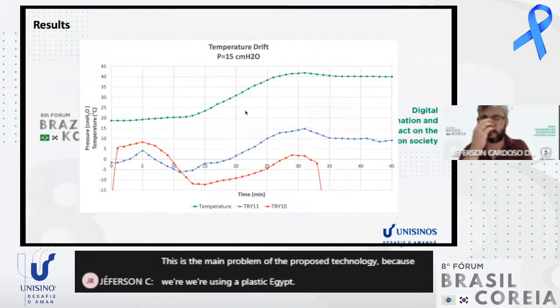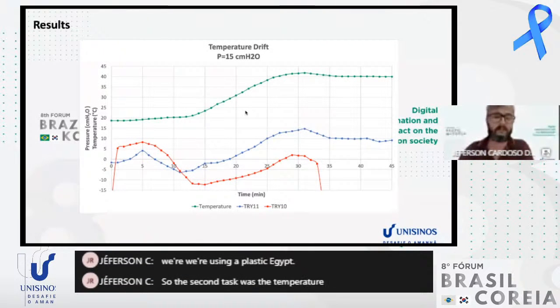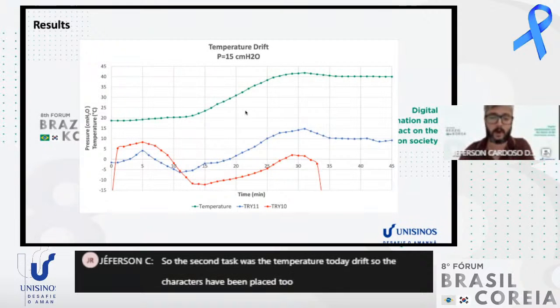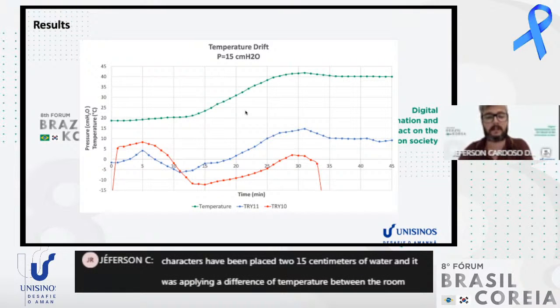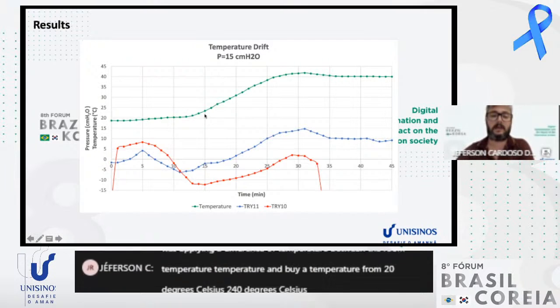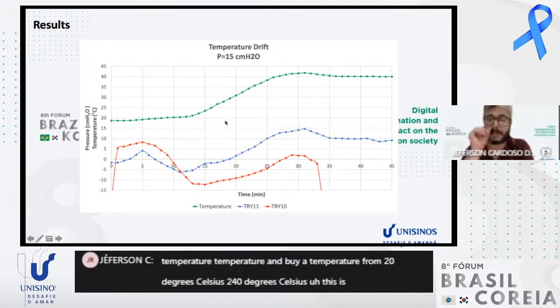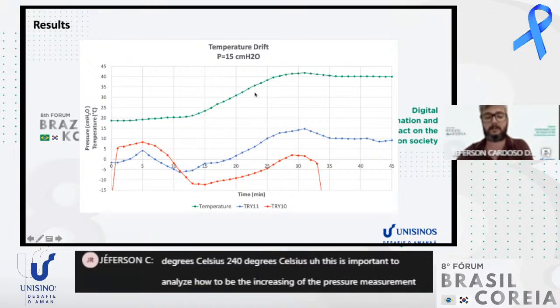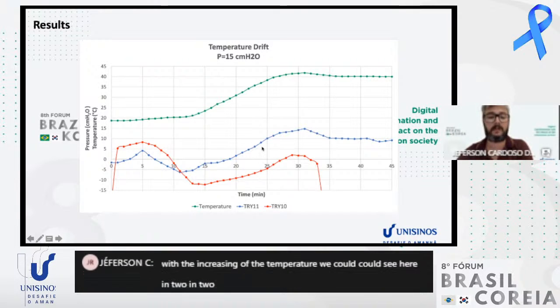So the second test was the temperature drift. The catheters were placed at 15 centimeters of water, and a temperature difference was applied, from room temperature to body temperature, from 20 degrees Celsius to 40 degrees Celsius. This is important to analyze how the pressure measurement increases with the increase of the temperature. We could see this in two different prototypes.